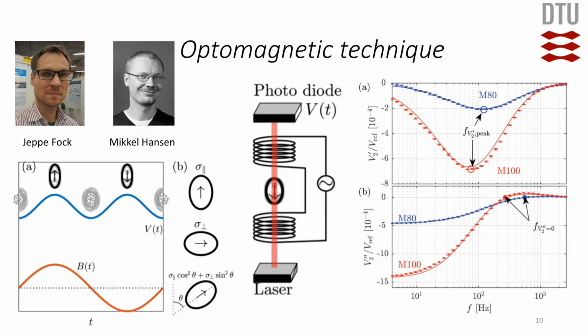But what is important now is just to see the real part of the magnetic spectra, the top plot. Here we compare 100 nanometer and 80 nanometer magnetic nanoparticles. They have a slightly different frequency at which the curves have a maximum value of light intensity, because the smaller nanoparticles can follow the magnetic field of higher frequency than the larger nanoparticles.